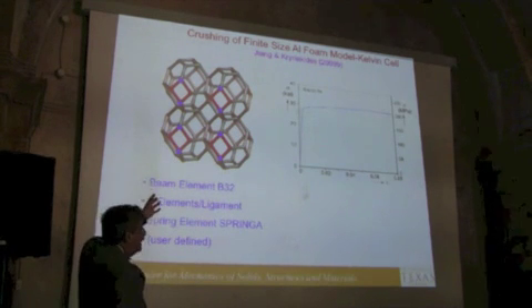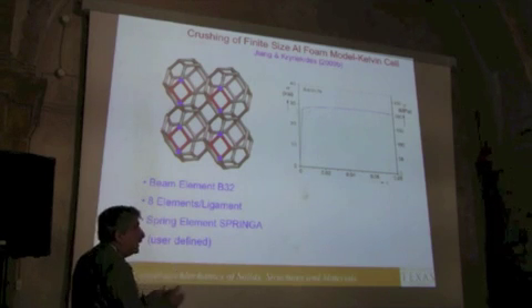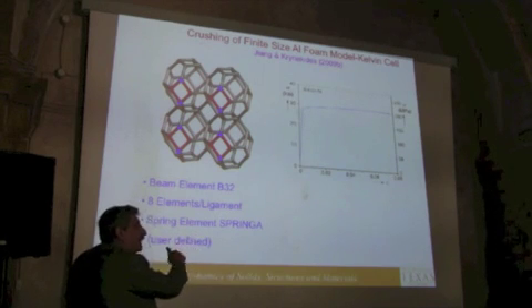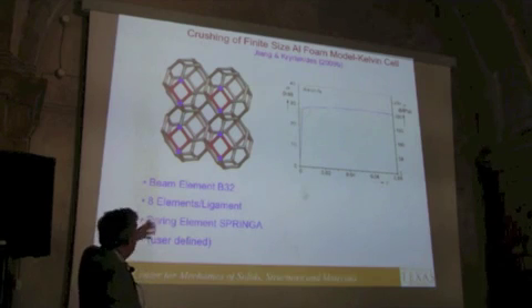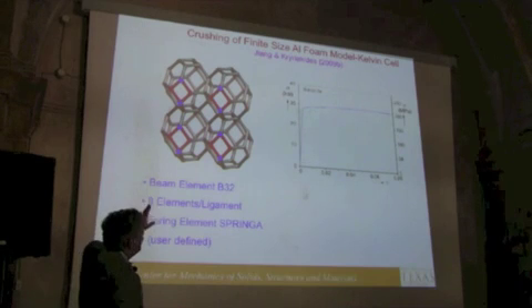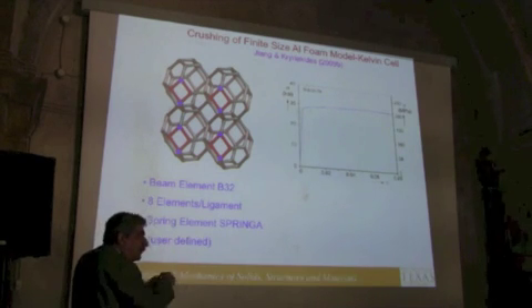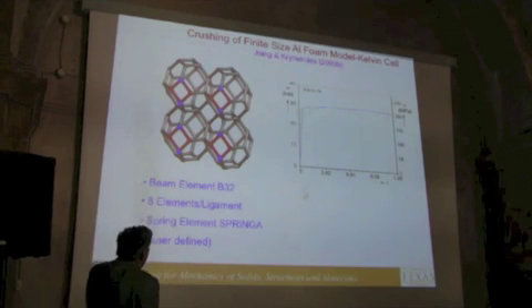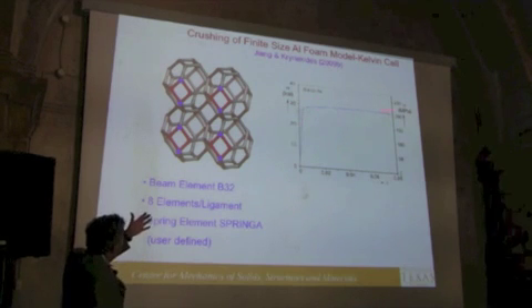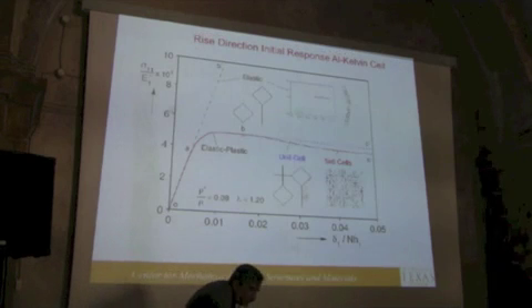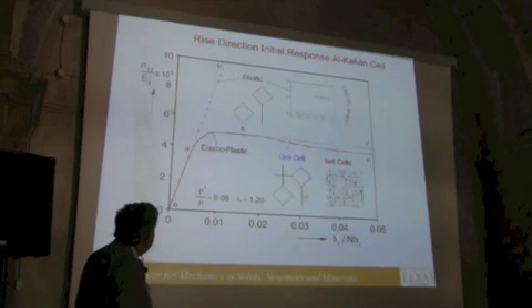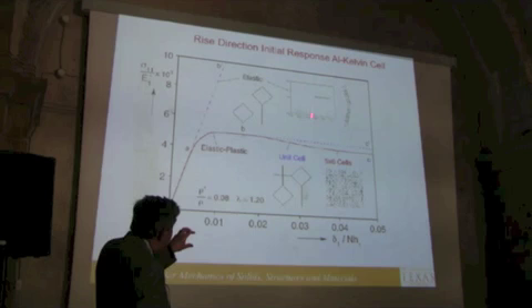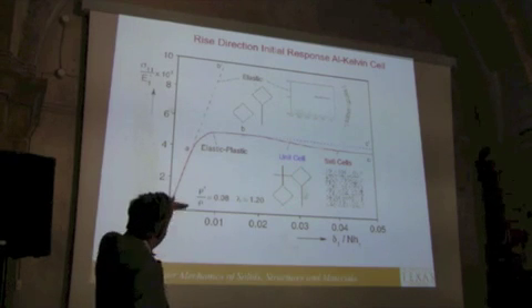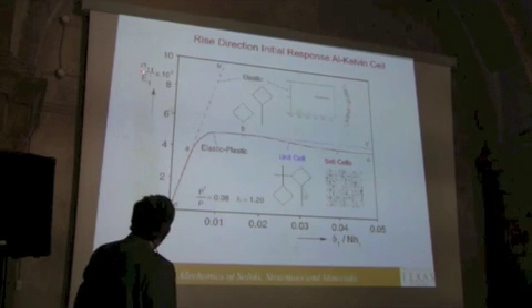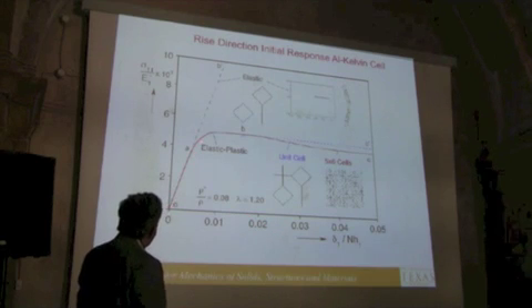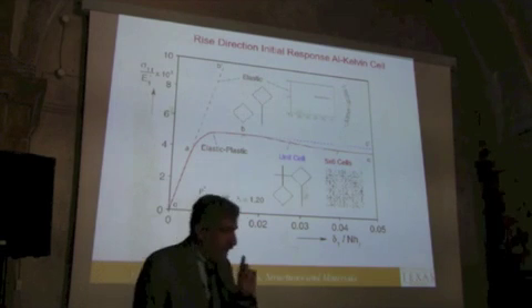Now, once you regularize this, you have a characteristic cell, and you can get most of the properties, the elastic properties and the onset of the instability, but you cannot get the crushing. In fact, the elastic properties, there are plenty of them here because it's anisotropic. You can get them from quite simple beam models of the characteristic cell. The base material response is shown here. It's an aluminum. If you put those into a characteristic cell, this is a calculation of a fully periodic characteristic cell, and you crush it, then this is what you get: the stress versus the change in height, elastic behavior, inelastic behavior, and a limit load.